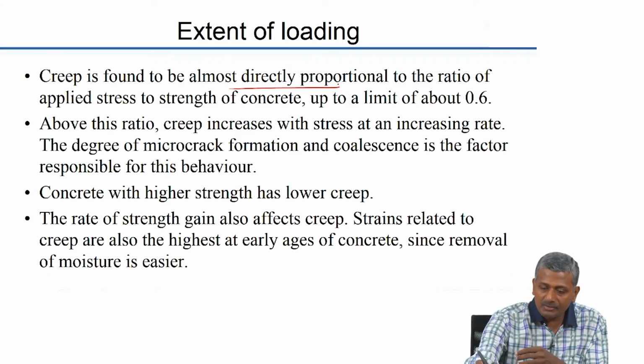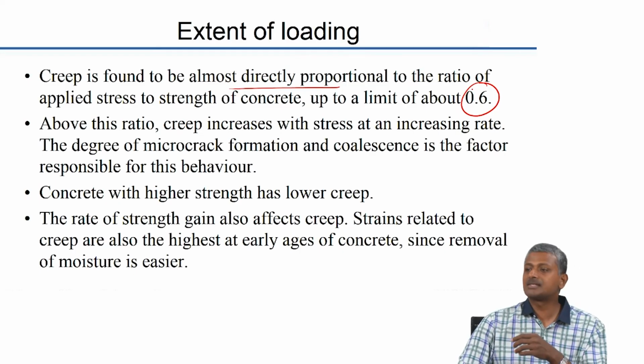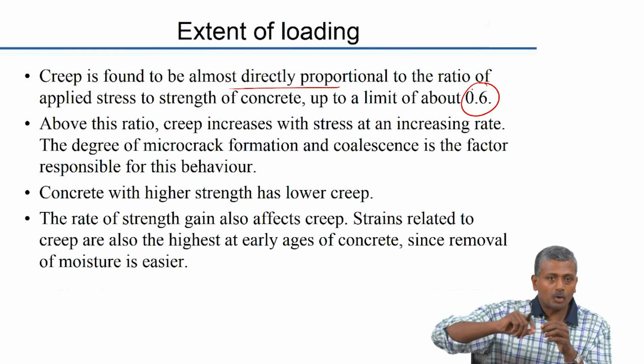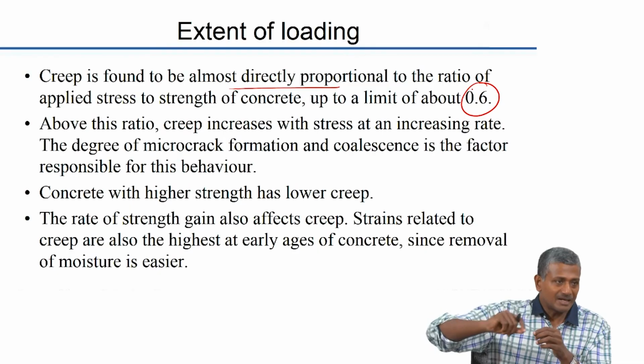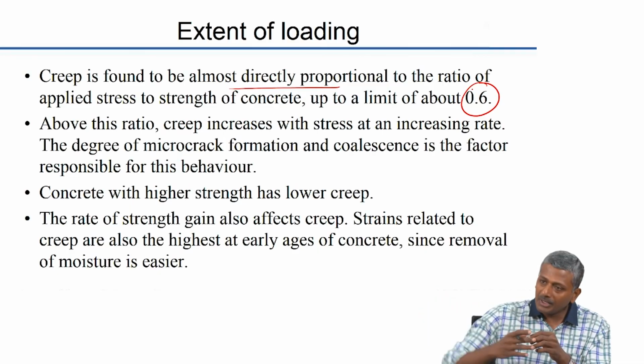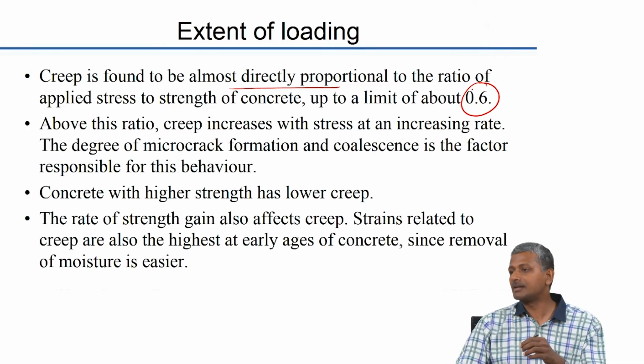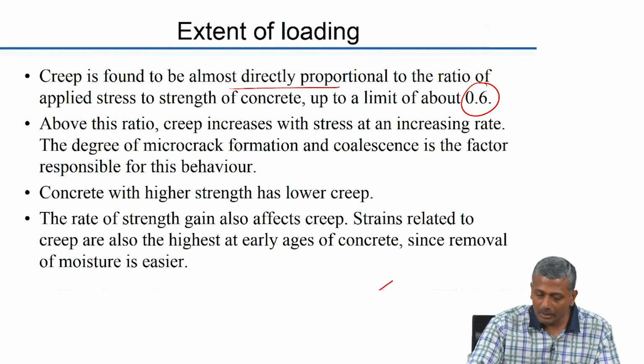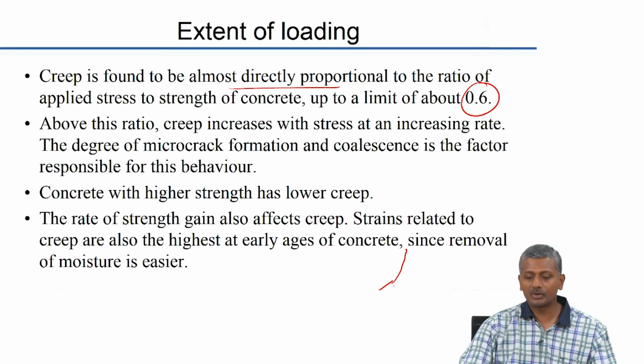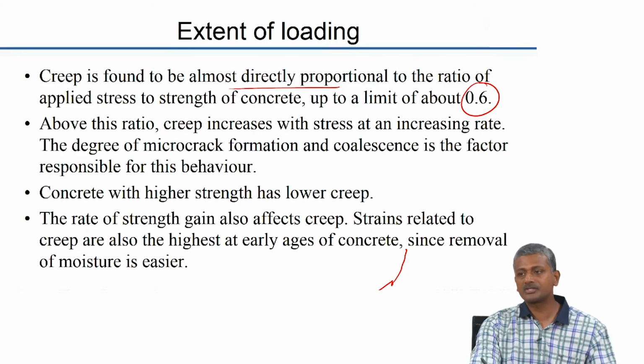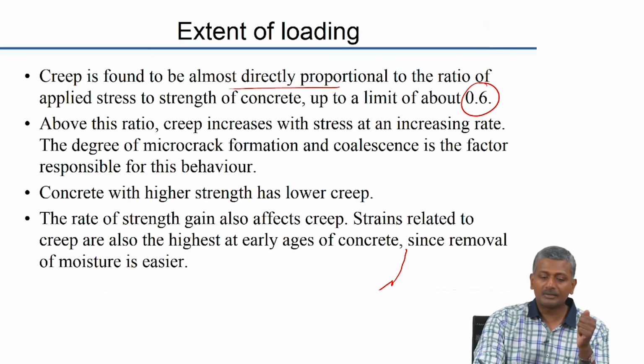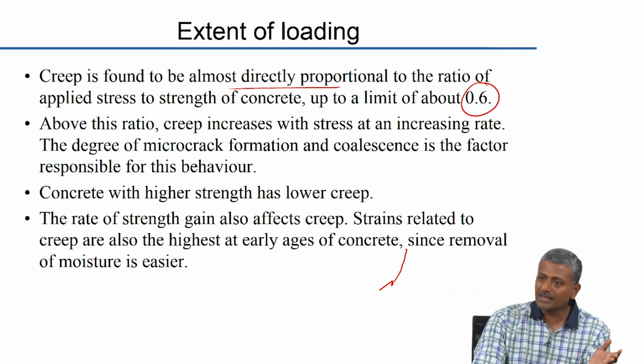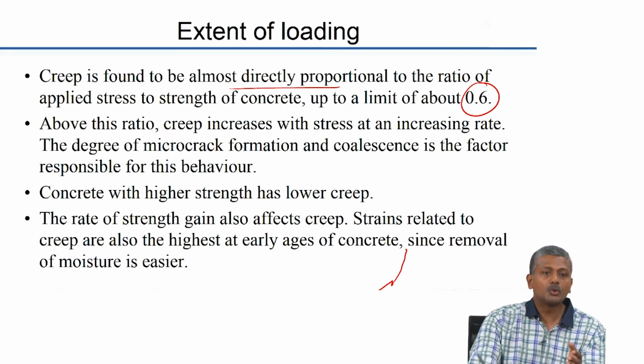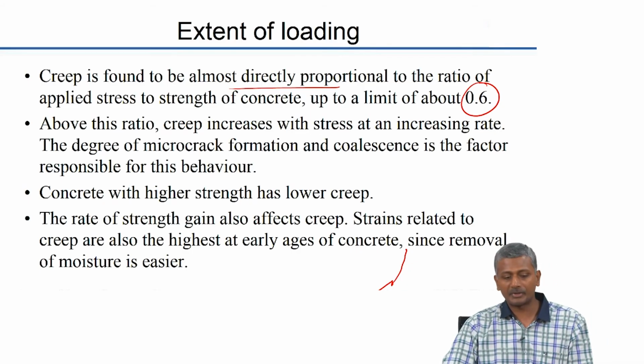Now, when your applied stress to strength ratio exceeds 60%, we saw that the cracks also start propagating into the matrix. So, when that starts happening, the creep increases at a much faster rate. Okay, it is not linear anymore, it starts increasing at a much faster rate beyond 60% of the load, okay, beyond 60% of the ultimate load. So, again the degree of microcrack formation and coalescence is a factor responsible for this behavior, and that is again associated with the behavior we saw during loading of concrete in uniaxial compression.